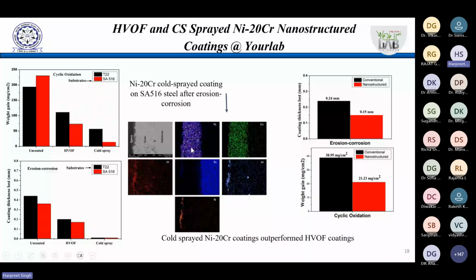this work was done, and we could again develop very nice coatings. Of course, we could not deposit 100% waste here, because the nickel and chromium recovered from the waste was in the nano size, so it was difficult to move through our powder feeder. But we added some fraction, 10%, 20% of those recovered powders from the waste into the new powder, right? At least some fraction of the fresh powder we are saving. And again we characterized them, we tested them in the actual boilers and all that, and we could again see very nice benefits of these coatings.